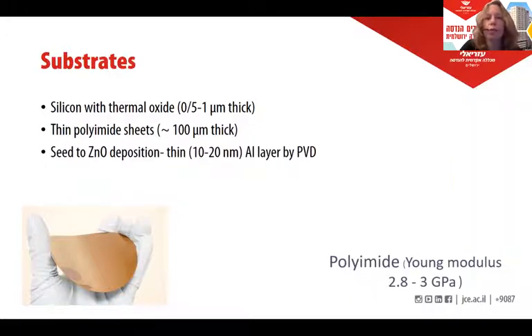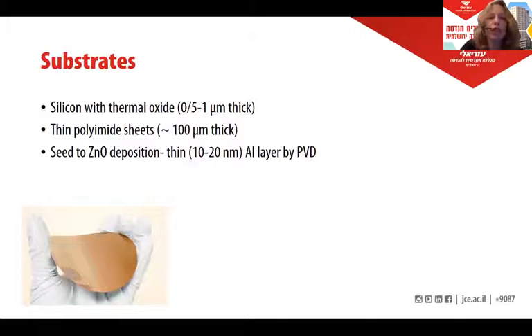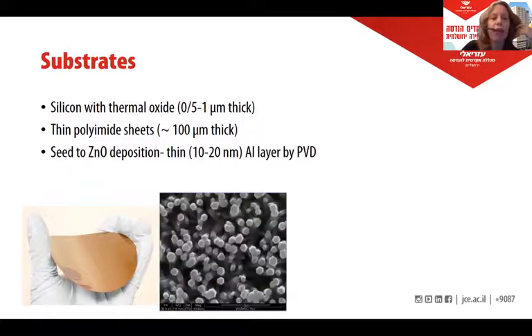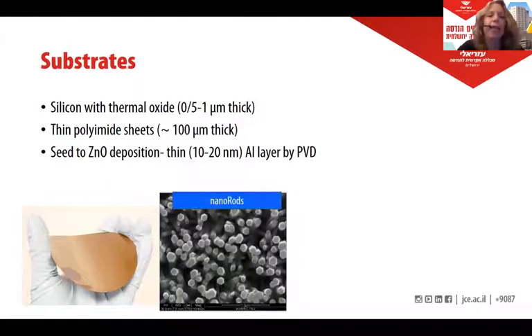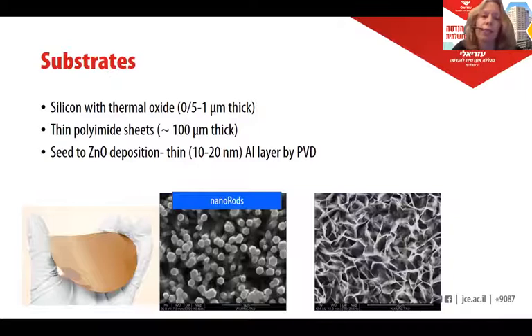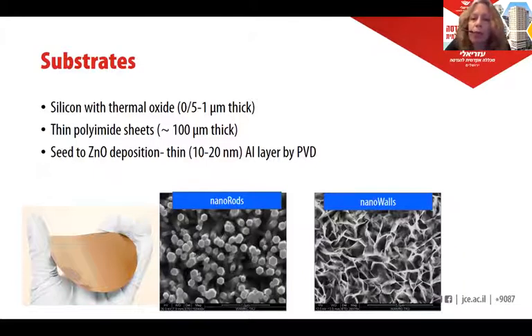On the substrate, if it's silicon or polyimide, nevertheless, we need to deposit the ZnO on a seed layer. If we did not deposit on an aluminum seed layer, we get nanorods. And if we deposit on an aluminum seed layer, we get nanowalls. And the thickness of the wall is about 20 nanometers. And the advantage of nanowalls over nanorods is the large surface to volume ratio. If we want to make it a sensor, we need a very large surface area. So we prefer the nanowalls rather than the nanorods.